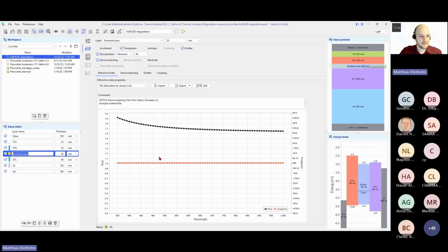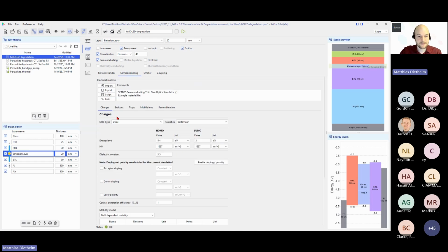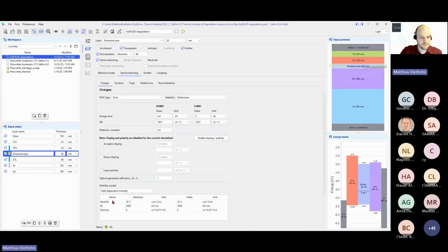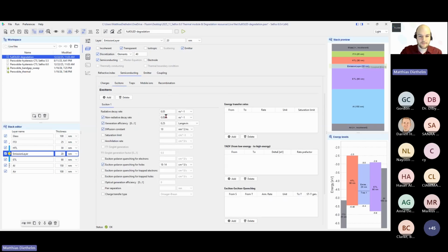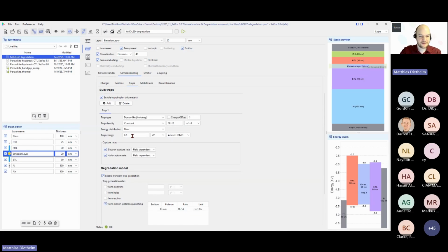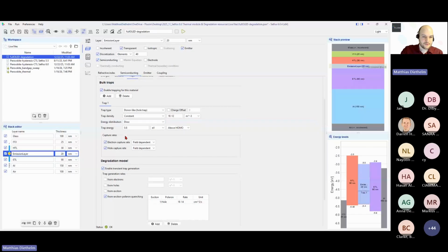That's the optical parameters here for the emission layer with refractive index, real and imaginary for absorption. And then, of course, also for drift diffusion, you define your parameters for the charges and, for example, also the charge mobility, which you can see here is in OLEDs often field dependent. You define your excitons, or your one exciton in this case of this example. And importantly now, you can define your trap here. So we have one trap defined, and you can here put in the trap energy. Conveniently in the energy level section here, you can see also where your trap is situated according to the parameters you set. You have here capture rates.